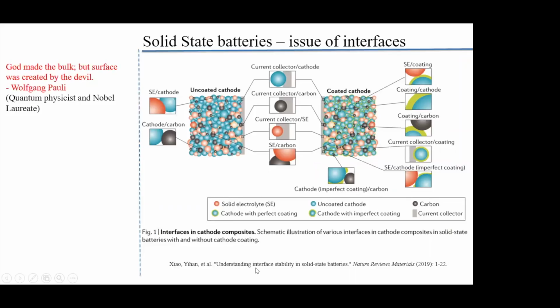This is from the paper, Understanding Interface Stability in Solid State Batteries, in a pretty prestigious journal. People can go into this journal paper and read more about it. But basically, you can coat some of the cathode materials and then mix them with the solid electrolyte particles. And you still need to ensure the contact is good, because if the contact is not good, it leads to a hotspot. It's like a tiny hotspot that can grow and grow and then lead to catastrophic failure. So that's the problem. The interfaces are something they must solve.